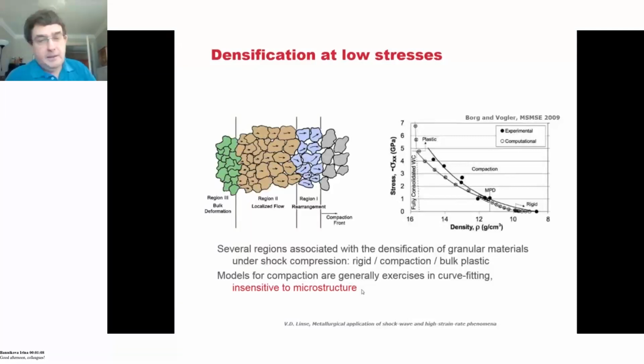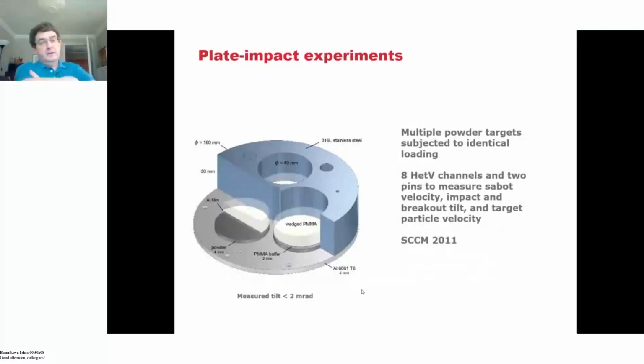You can do plate impact experiments, and this is some work that was presented at the shock compression of condensed matter meeting in 2011. Put various channels on there and put powders of different initial densities and perform an impact on the powders and measure the particle velocity at the rear of the powder, and from that derive a shock relationship.